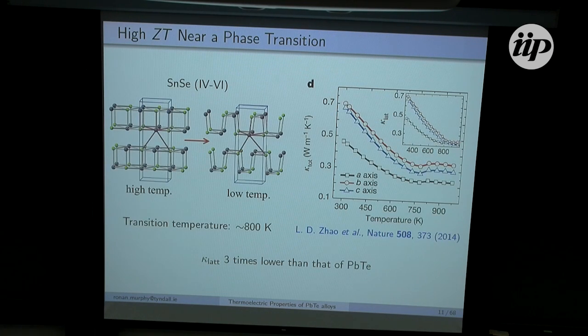So now I just want to talk a bit about this. That was all a little bit hand-wavy, but if we take a look in the literature for an example of a high ZT material near a phase transition, there's tin selenide. It's a group IV-VI material like lead telluride, and it undergoes a phase transition as a function of temperature. Here is the high temperature phase, it's orthorhombic, and you can view this as a distortion of the rock salt phase. As you lower the temperature, there's a phase transition at about 800 Kelvin, and the structure transitions to a lower symmetry structure. You can see what that looks like here.